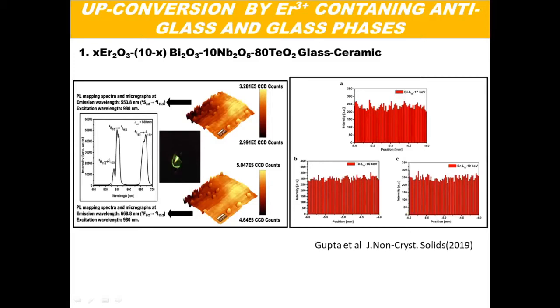So you see green light coming out of the sample because the erbium ions show upconversion by a process which is known as ESA, excited state absorption. Two photons of 980 nanometer are absorbed and they take the erbium ions from one excited state to the next higher excited state. And then we see the green light emission at 553 nanometer. So we are having a transition from the S state to the I state.